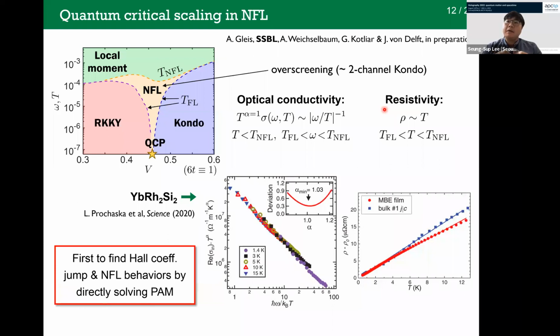Yes. So basically, we can understand the physics here as a two-stage screening. So let's consider, again, let me just annotate. Say we consider this vertical line as some kind of RG flow. And then as I showed earlier, in the context of Hund metals, at highest energy scales or temperatures or frequencies, we can regard just decoupling, pure local moment. Of course, at much higher energy scale, we will see the free orbital regime where the charges are also flowing. But this is a very large scale. It will be of the order of 10, which is on the scale of U. And we go to the local moment regime. And the first some degrees of freedom are screened. So it is not as simple as in the Hund metal, it's much more involved, but leading to this intermediate non-Fermi liquid regime. And after the second screening on the scale of this T Fermi liquid, then we go to the Fermi liquid regime.